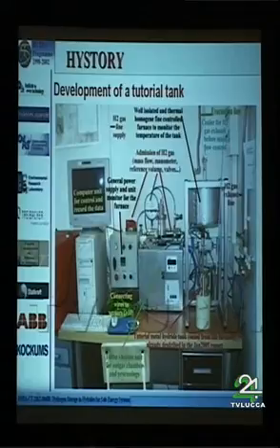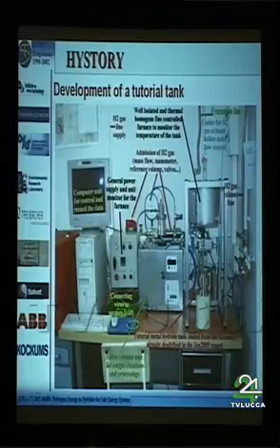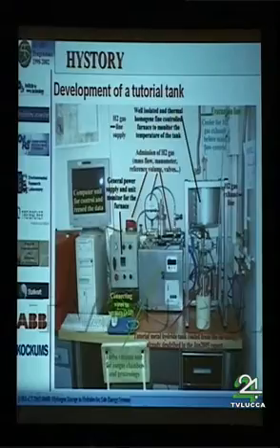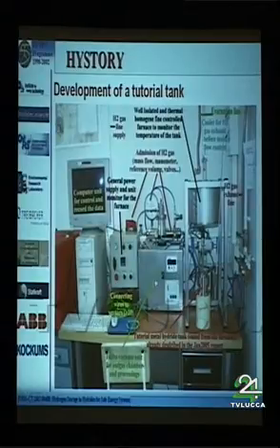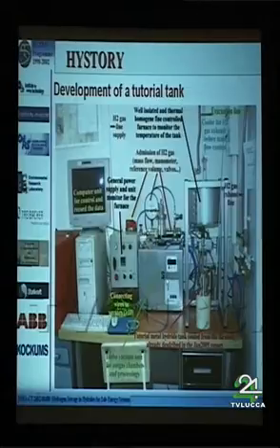At the laboratory scale, we have effectively built a tank. It is installed in this furnace system, for example, to activate the material first. And we have a lot of ancillary equipment. For example, we have a vacuum line to get a very good vacuum on the powder and to get a very nice and reproducible result.